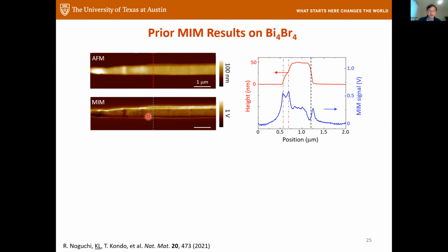On this side, you clearly see this double feature. This one we know very well. When the tip approaches here, it sees more material, and when the tip climbs up a step, it sees less material. So when we see this, we say, okay, this is not real, this is just a topographic artifact. But on the other edge, you see fairly nice bright lines. Or if you don't trust me here, you can look at this one. Here you don't see the double feature anymore. It's just a bright line.